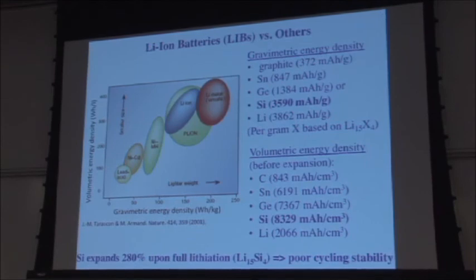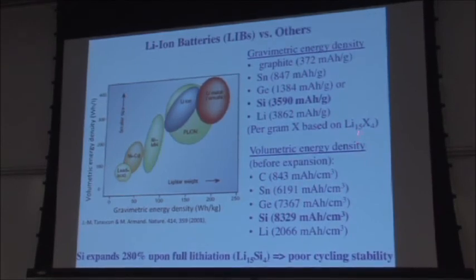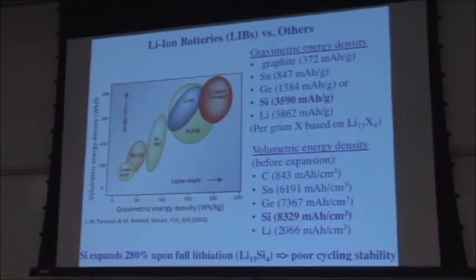And if you look at it by gravimetric capacity, and this is Li15Si4, you actually don't reach the 4,500 capacity reported earlier by authors. So basically this is the terminal phase, Li15Si4. The capacity is almost on par with metallic silicon, the gravimetric energy density. If you look at the volumetric energy density, this is kind of neat. It's actually significantly higher than that of lithium.